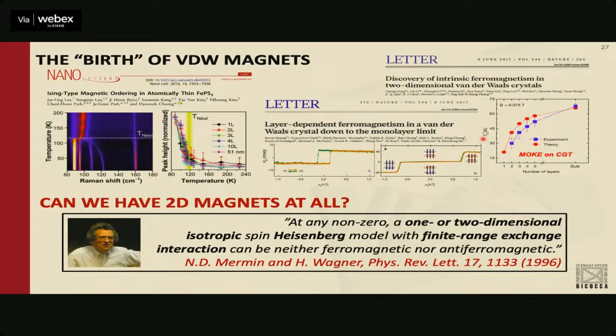Because what people thought was based on the so-called Mermin-Wagner theorem. So the Mermin-Wagner theorem says what? That if I have my spins, and my spins are isotropic in space, then in dimension lower than 3, you cannot have long-range ordering developing at all. And so the discovery of having magnetism itself in a 2D material was a kind of surprise.